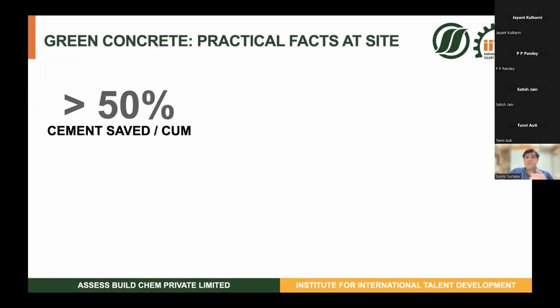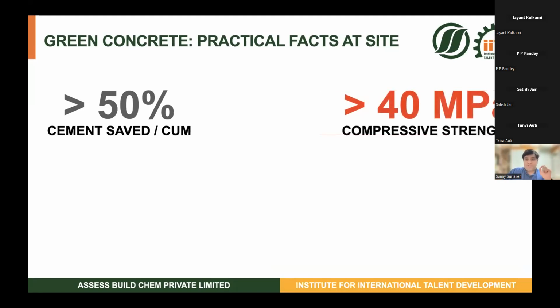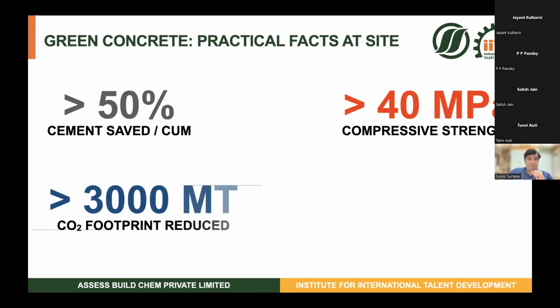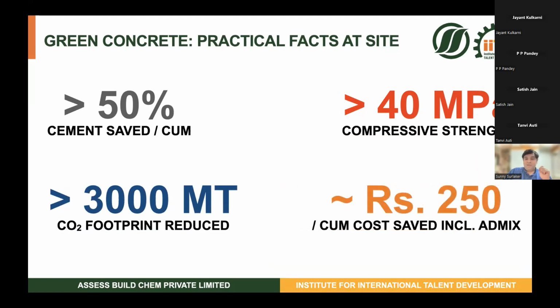So on the practical side, we said it's not enough that we simply do all these things in the lab. We also took a look at what kind of results we're actually seeing on the site. What we saw was more than 50% of cement was saved. The compressive strength that we got from cores was consistently over 40 when the requirement was about 35. And over the course of the project, the carbon dioxide footprint reduced by more than 3,000 metric tons. And the cost, of course, we had very good cost savings with that particular type of mix.